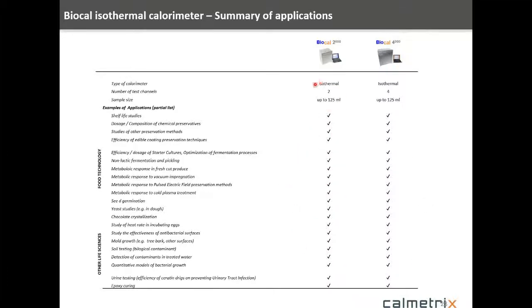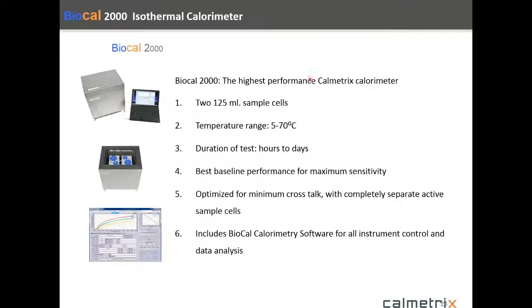There are differences. The 2000 has 2 channels, so you can run 2 samples simultaneously, versus the 4-channel device, which can run 4 samples simultaneously. So this is double the throughput basically. And there are other differences. The 2000 is considered our highest performance calorimeter. It does use 2 of the 125 milliliter sample cells. The sample cups themselves between the 2 instruments are identical. This uses 2 of them simultaneously, so you can run 2 samples.